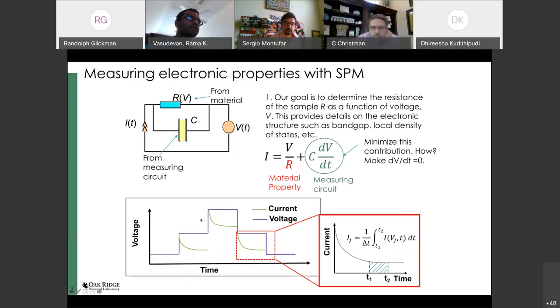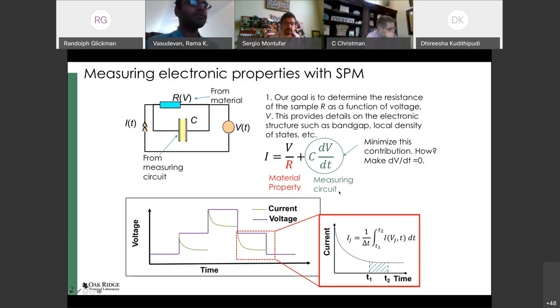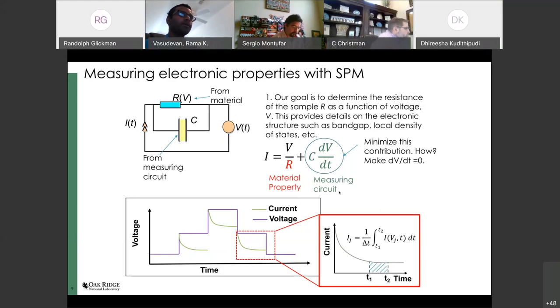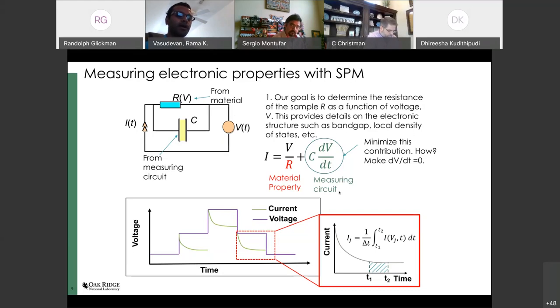In practice, this is done by stepping the DC voltage in a waveform and applying a delay time T1 before acquiring current. After every voltage step, you integrate between times T1 and T2 to capture the steady-state current and minimize parasitic capacitance. However, this is slow because both the integration time and delay time must typically be on the order of milliseconds. With many voltage steps, it adds up to at least half a second to one second per IV curve.